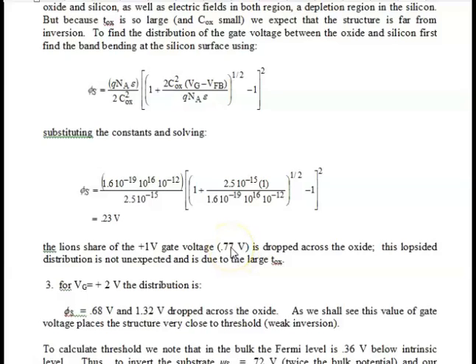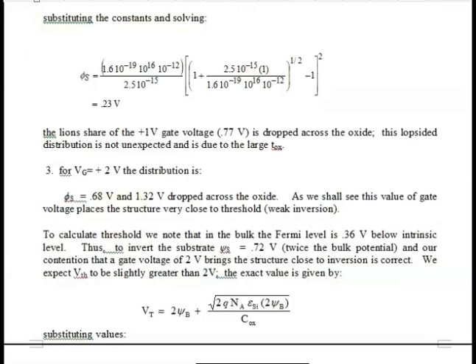And of course that is consistent with the fact that the smaller the oxide thickness, the more control the gate has over the oxide surface. Okay, that's a mouthful. And finally, if we put a gate bias of plus 2 volts, we would expect both of these numbers to go up. It may be in depletion, it may be in weak inversion, or maybe inversion, but one thing's for darn sure, it ain't in accumulation. So we're moving now from a depleted region, possibly either into weak inversion or strong inversion.